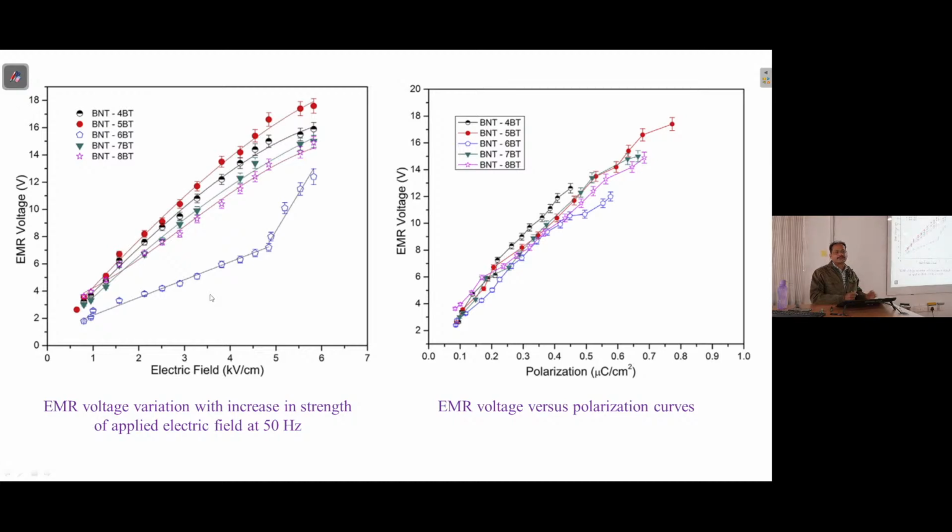So that resistance is dominating at the lower voltages. But when we go for a higher strength of the field, we get the benefit of the large number of polarization directions, and that becomes dominant, and thereby better performance is achieved. So considering this variation, we can see that if we could go for higher fields, this will surpass all this, and finally the usual thing that is observed will be observed for this case also.